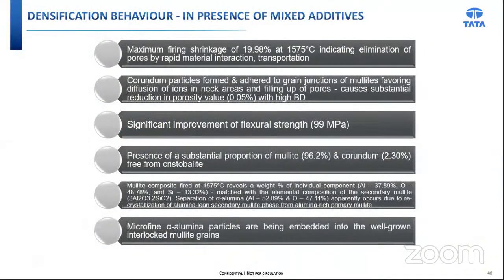Now, for the mixed additive, while we put 0.75% boehmite and 0.75% yttria into the matrix, exceptional properties have been achieved. Desirable phase assemblage along with a uniform, dense and homogeneous interlocked microstructure of the mullite-based composite has been observed at 1575 degrees centigrade. And this is the optimum scenario.